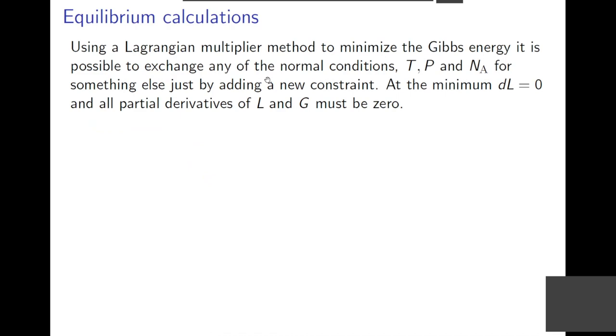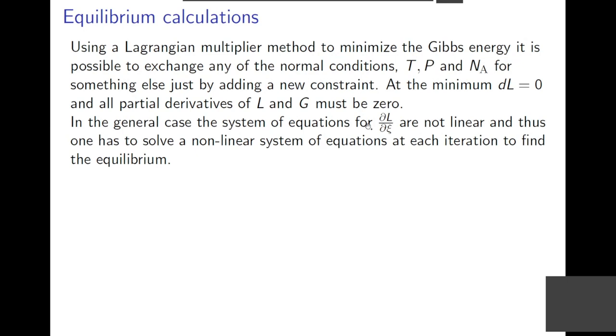So with this Lagrangian multiplier, you basically have a way of determining the composition of individual phases and the amounts of individual phases by just prescribing that your differential for the Lagrangian multiplier should be zero. And that means all the partial derivatives for the Lagrangian should also be zero. But if you do it straight away, it means you have a nonlinear system of equations, and on each iteration you have to solve this system of equations, which can be quite heavy and not so stable.